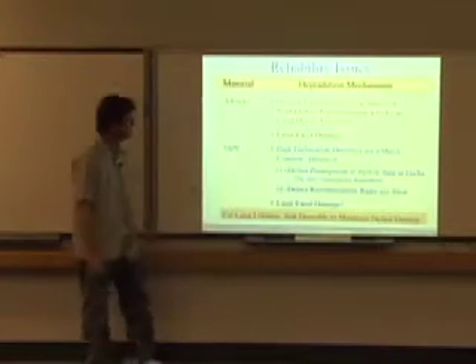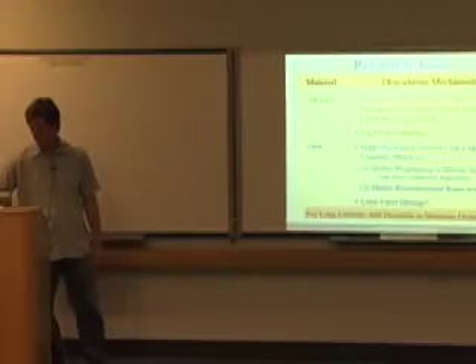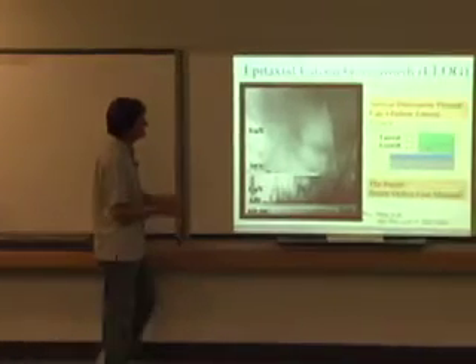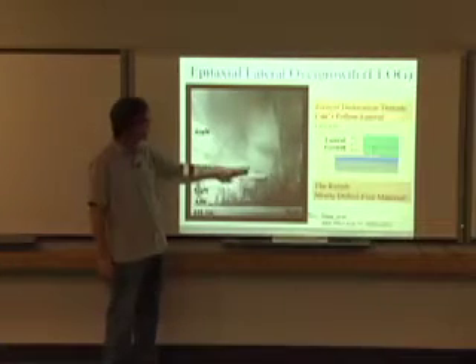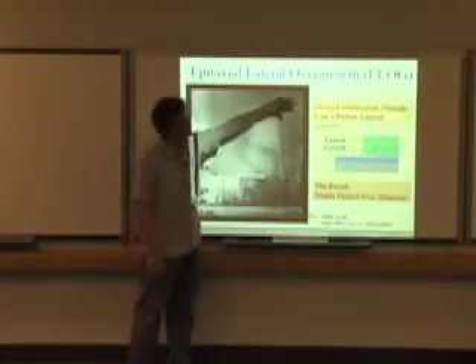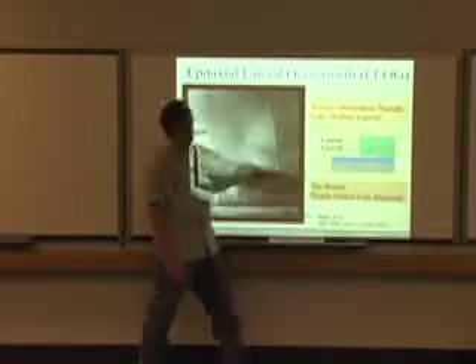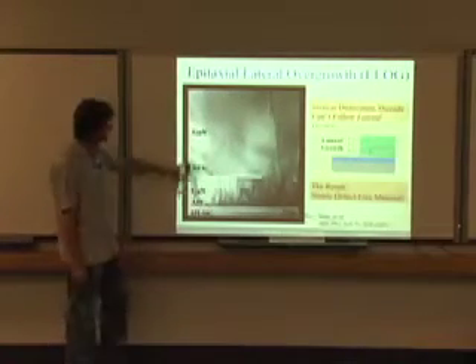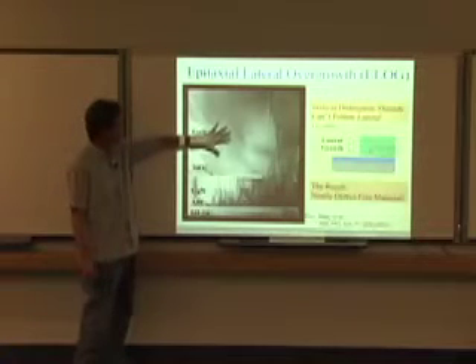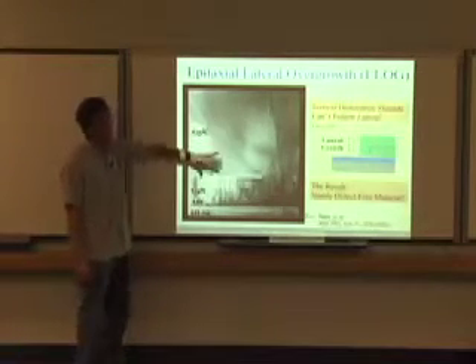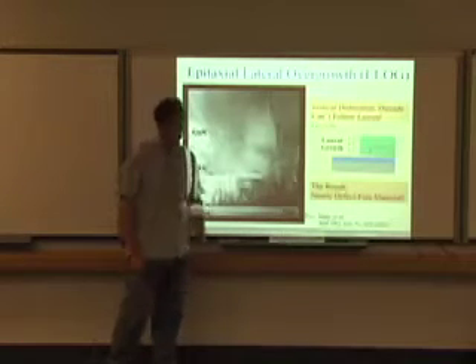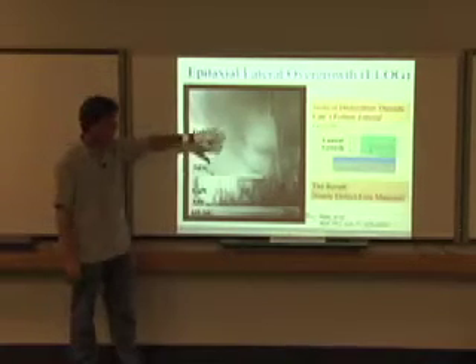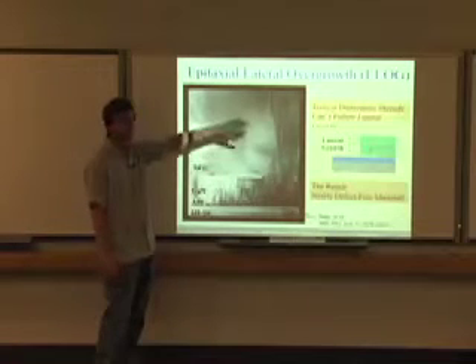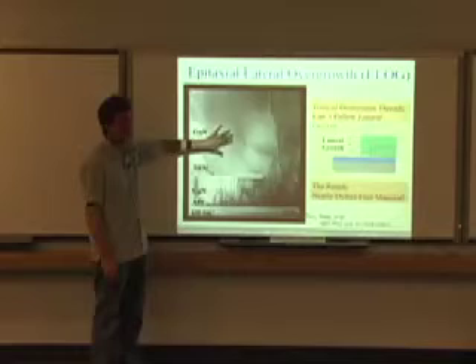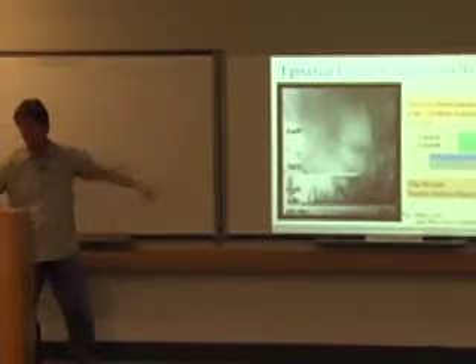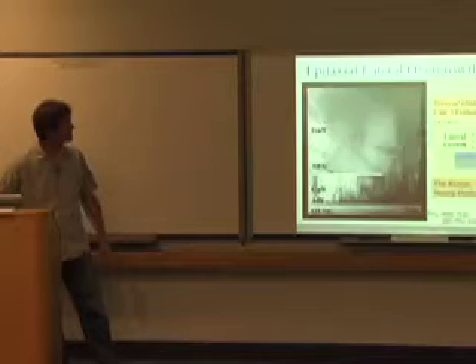But still, there's definitely a desire to minimize the defect density. And so one of the techniques that became popular was growing SiO2 over a gallium nitride layer, and then continuing growth, and it would come up and laterally grow over that oxide layer. And this is an example of that. You can see very nice, clean, relatively defect-free material on top of the SiO2. This ELOG was developed at North Carolina State, but others at NEC, and then Nakamura really just kind of ran with the football on this one. He just took it to town and used this for the laser technology. He just did great things with it.